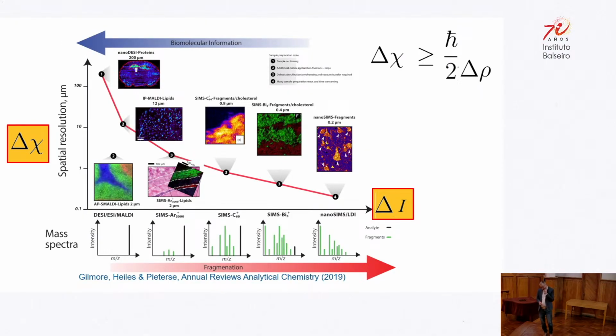So this is actually the physical reason why we have this uncertainty principle. Don't worry about the details on the slide, but on this axis here, we have the amount of fragmentation that's caused by the ion beam in the mass spectrum. And on this axis, we have the spatial resolution that we can achieve in the beam. So this is a measure of the uncertainty in the identity of the molecule. If we have a lot of fragmentation, then we obviously don't have the original molecule, so our uncertainty is very poor. And we have a very high uncertainty here.